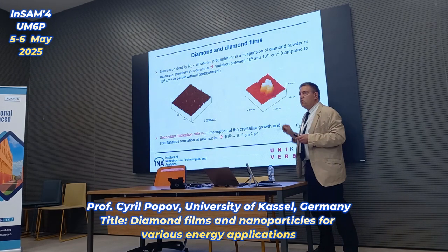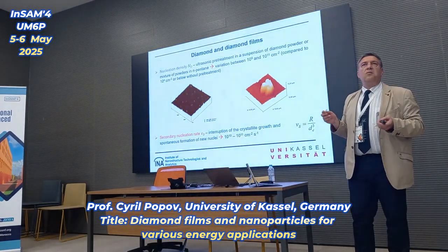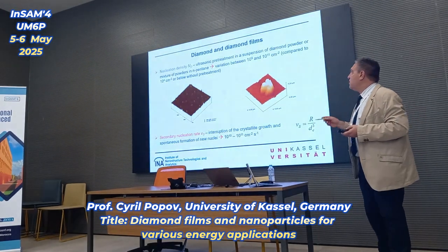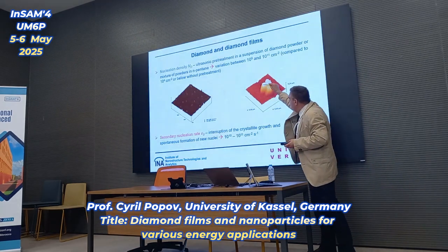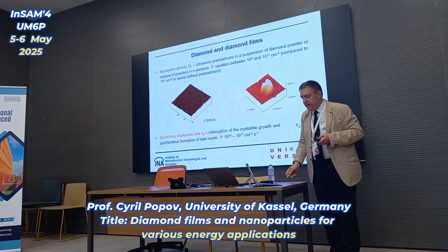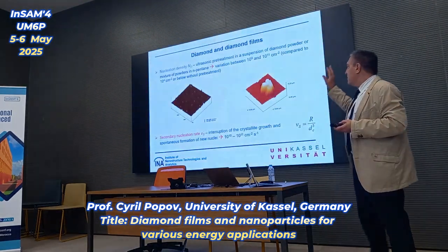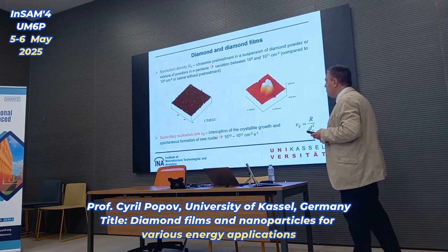And also these scratches serve as nuclei for the growth. And what you see here, these are in fact two diamond grains. We say it's a twin grown on such a defect. So in this way, we create the defects or the nuclei for the growth.